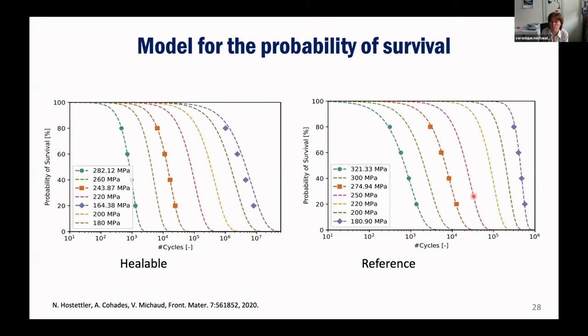And then we decided to do some healing cycles. For this, we had to do quite a bit of work to try to model the probability of survival and say, we want to do the healing cycle when we are at maybe 90% probability of survival of our part. So for the healable and for the reference system, if I want, for example, 80% probability of survival, and I'm at 320 megapascal amplitude, then I have to go here. And then if I go here, I know that I should stop after this amount of cycles. And if I'm at, for example, 250 and I want 80%, then I know I can go up to 10 to the 4 cycles.